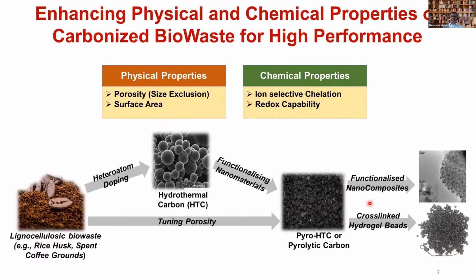Here I show you that one of my favorite feedstocks is spent coffee grounds. Who doesn't love coffee? The reason it is my favorite is not only because most people love coffee, but also because it's a very good material. It has a lot of protein residues, so it is highly functionalized, and hence it can be tuned for many different purposes. You can start with this, and then dope heteroatoms like nitrogen and sulfur, for example, to make hydrothermal carbons. This is how they look, beautiful spheres. Then you can functionalize nanomaterials by calcining or pyrolyzing them. You can also directly pyrolyze this material, of course. In the process, you can tune porosity. And then finally, products that we have produced in our own lab are cross-linked hydrogel beads or functionalized nanocomposites.